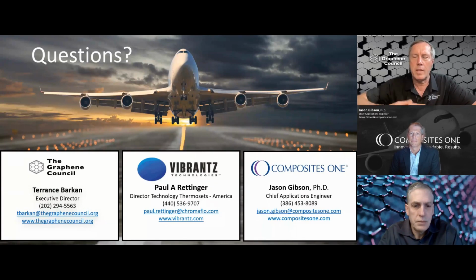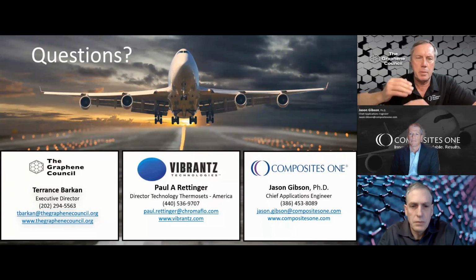So if you wanted to reduce flammability, but you want to increase strength at the same time, or whatever the combination is, or you want to use this with a carbon fiber or with a basalt fiber or with a glass fiber, you have a way of mixing and matching and tuning these graphene nanoparticles in different ways, because they can be changed with functionalization. They can be changed on carbon layer count, 1 layer, 3 layer, 5 layer, 7 layer. They can be changed in lateral flake size. You have all these ways then of tuning them, which really opens up opportunities to take your composite up a step change performance level with a really small additive.